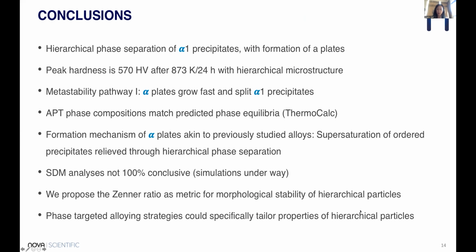Let's conclude this talk briefly. We saw hierarchical phase separation of alpha 1 precipitates with formation of alpha plates. Peak hardness is 570 HV after 873 Kelvin for 24 hours with hierarchical microstructure. The alloy follows metastability pathway 1. Alpha plates grow fast and split alpha 1 precipitates.